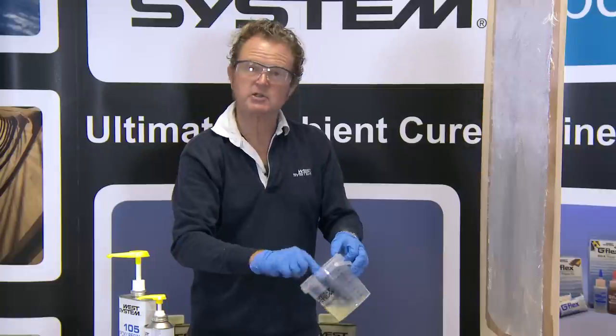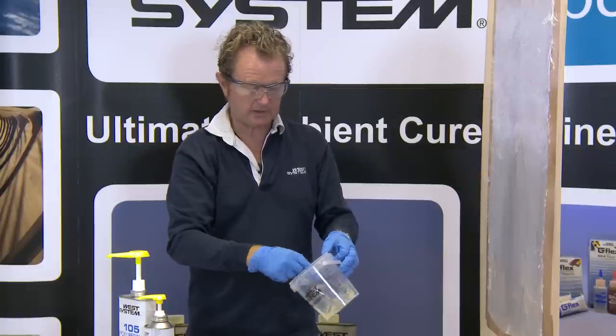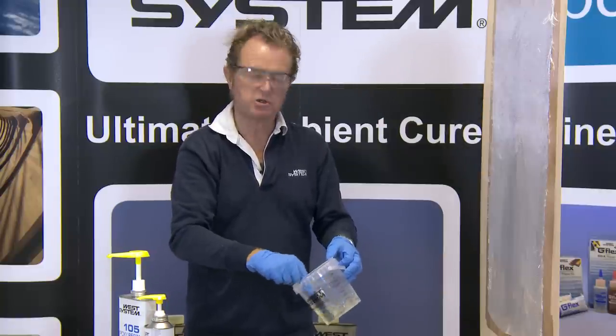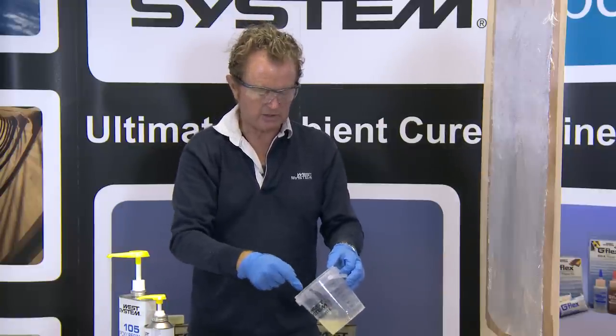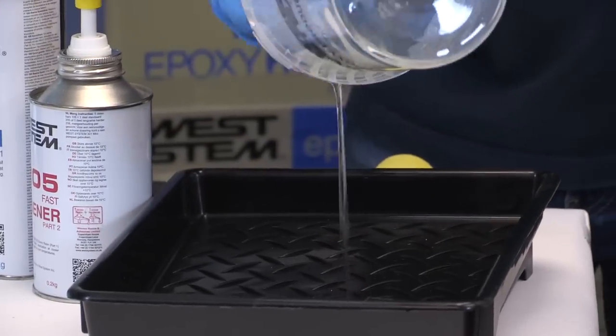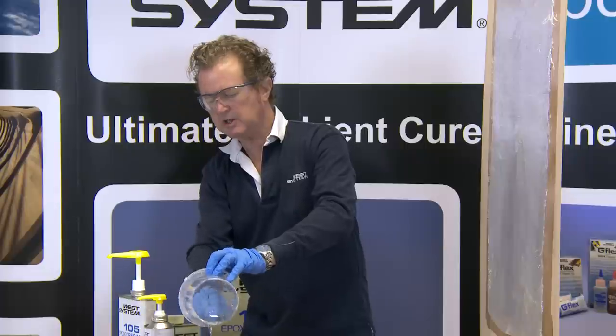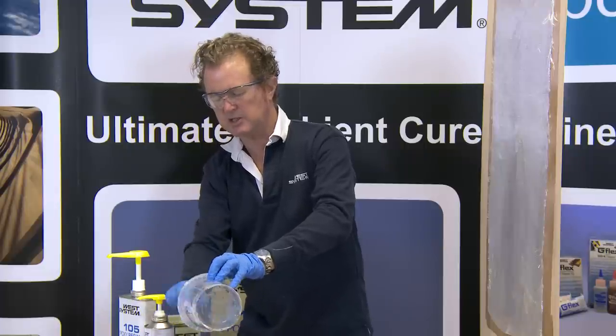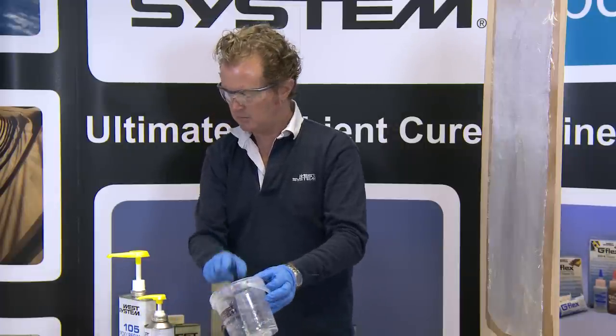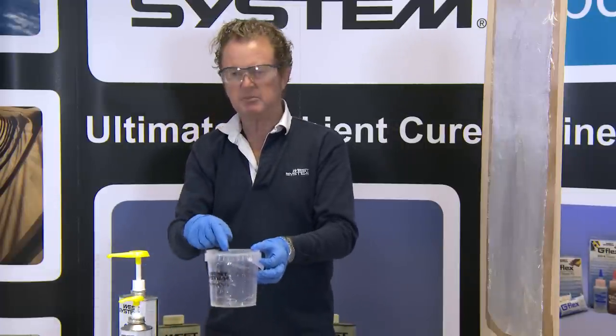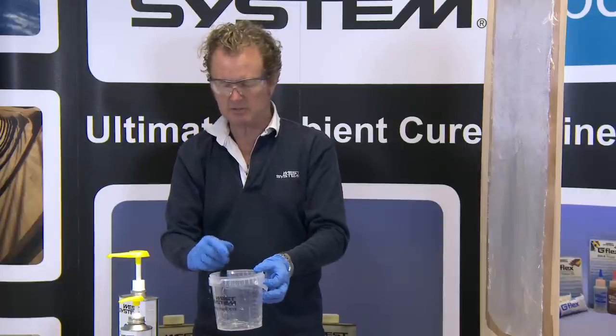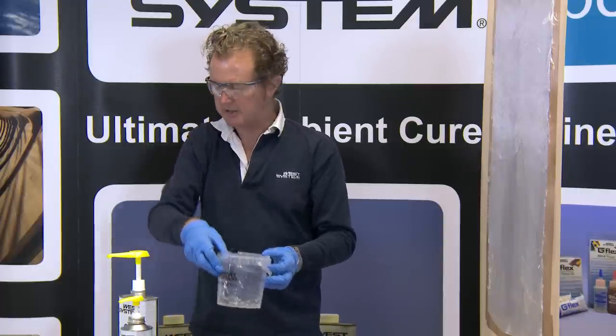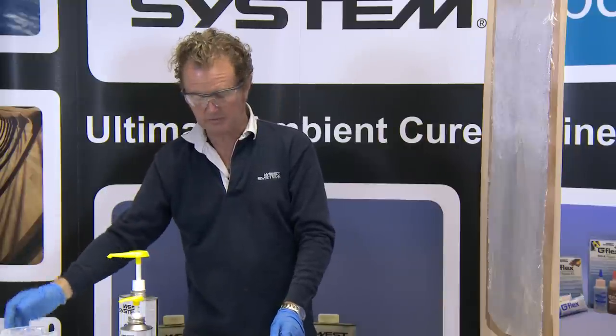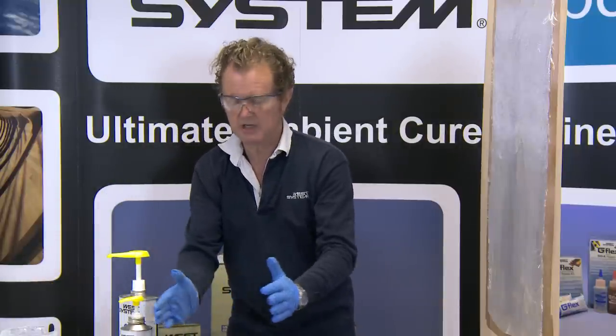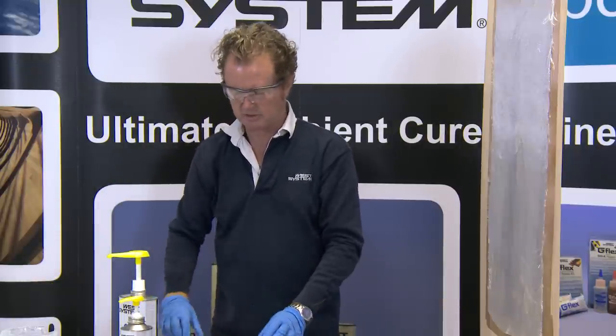So I've been mixing for 2 minutes now, and I've made a nice homogeneous blend of the resin and hardener. Dispense that into my roller tray. That will give me more working time. The working time of 4 pumps of resin and 4 pumps of hardener with the standard hardener in a mixing pot is around about 20 minutes. In a roller tray, I can extend that time to nearly double that working time because I've spread the volume over a broader surface area.